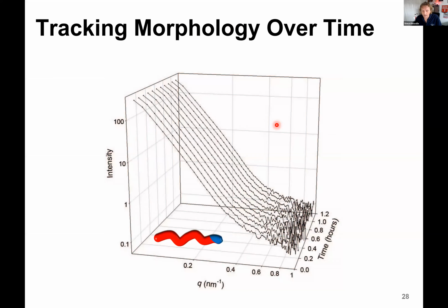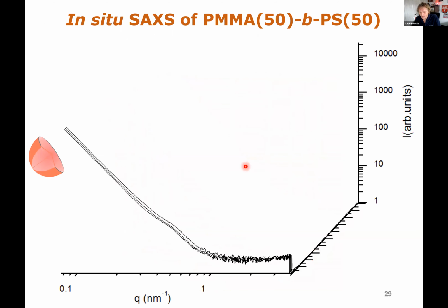We started to look at how in our polymerization, the scattering changed as the particles were formed. Here you can see what we saw. If we have the PMMA block first, and then a small amount of the polystyrene, initially we don't see anything. For the first hour of the reaction, nothing changes - this is a featureless hump here. It doesn't show anything. There's no structure.